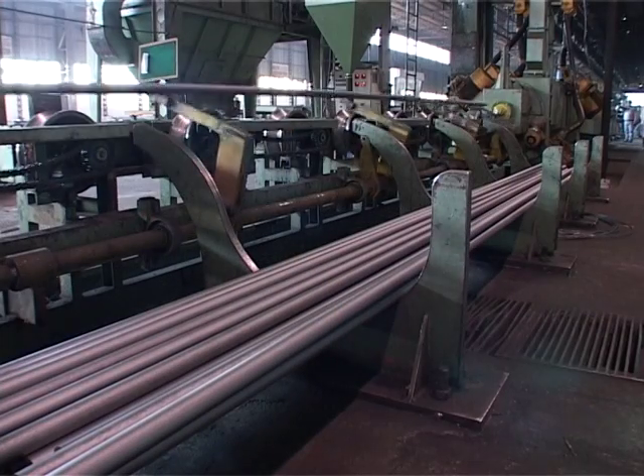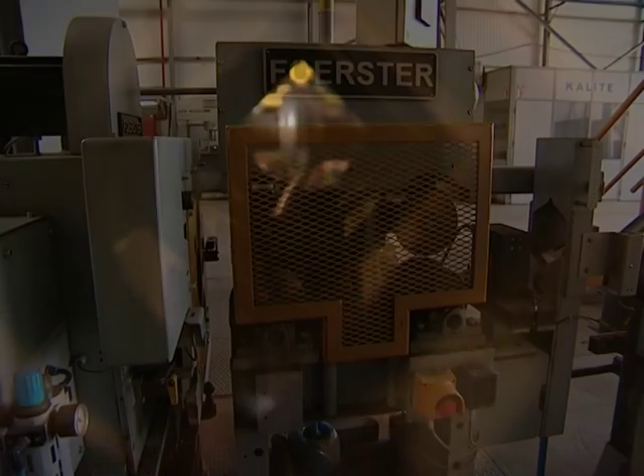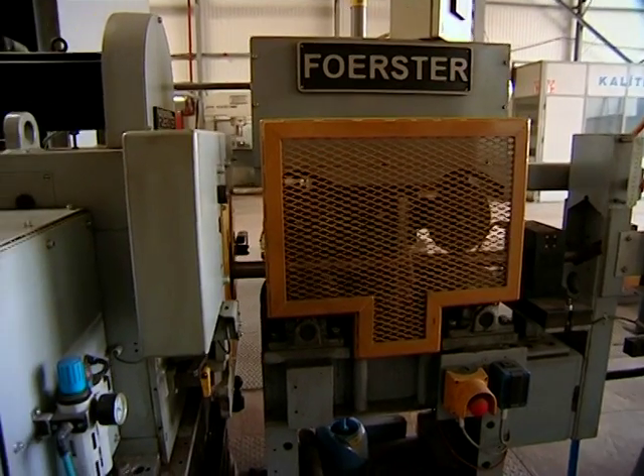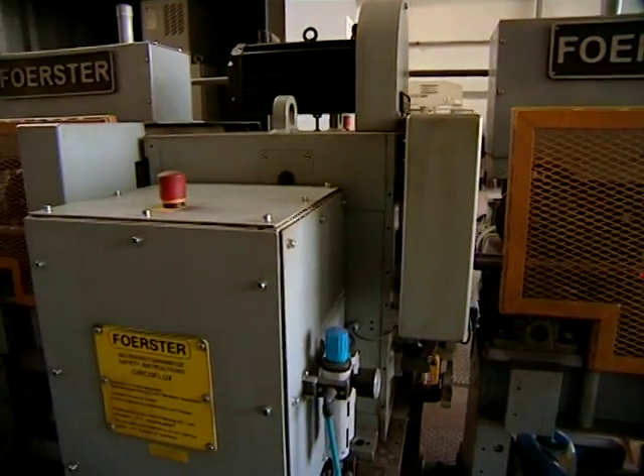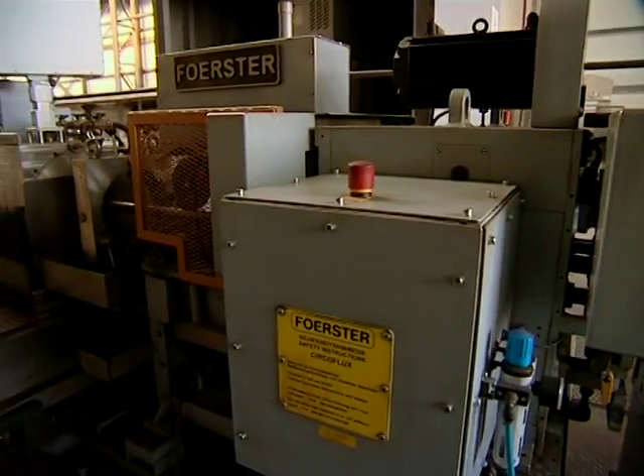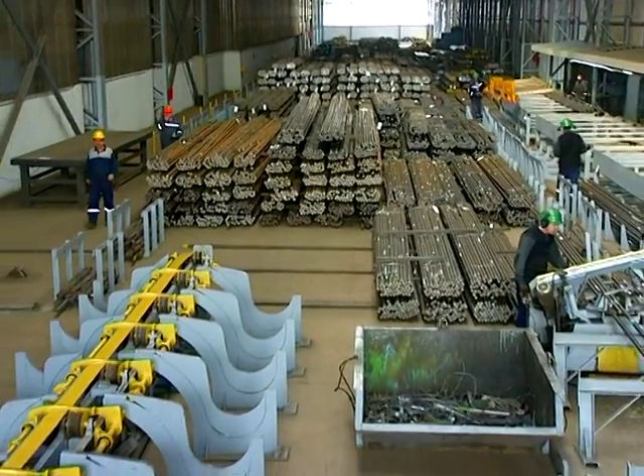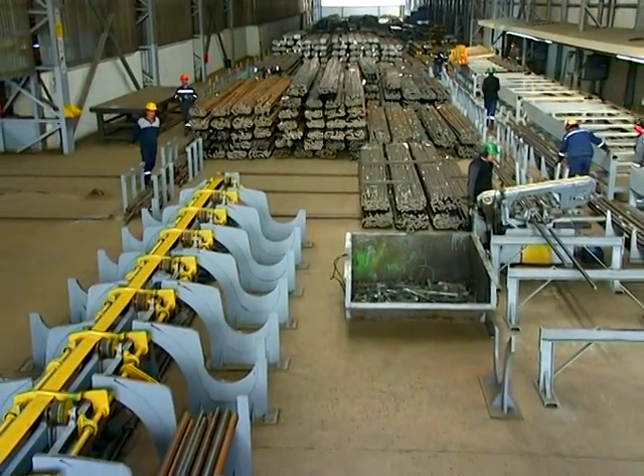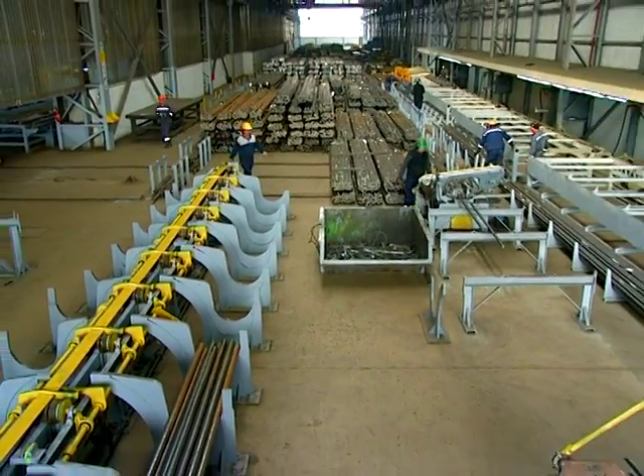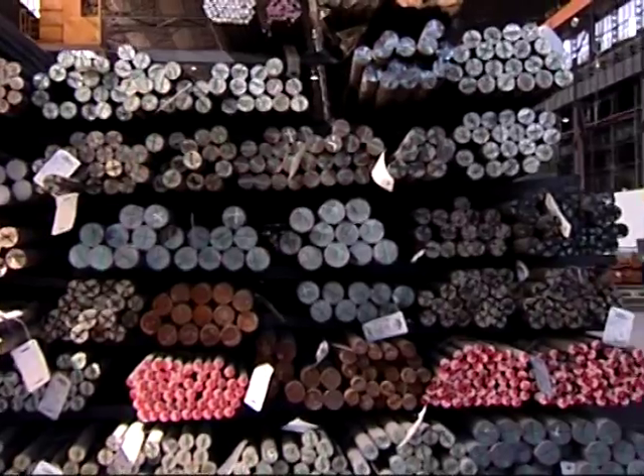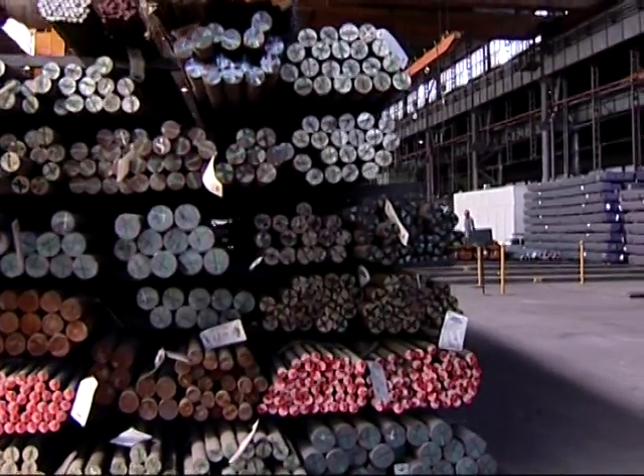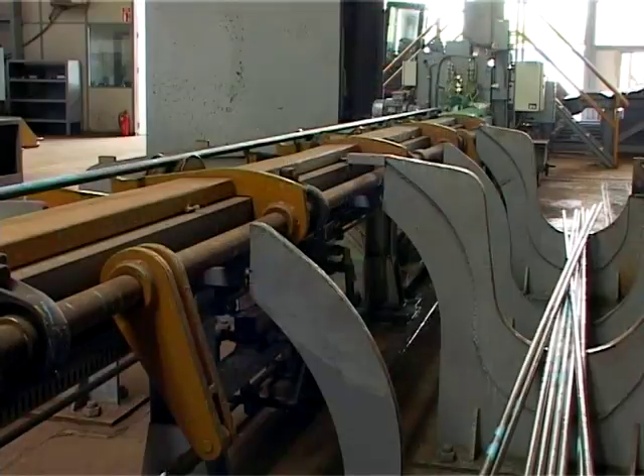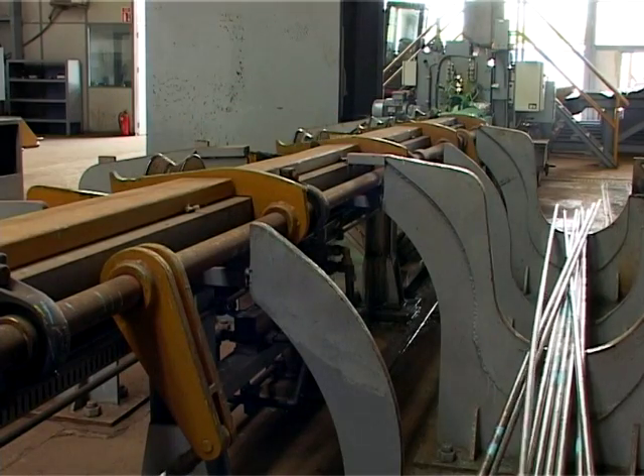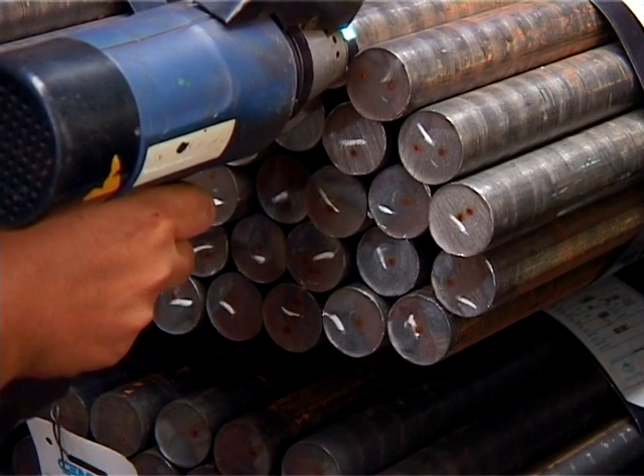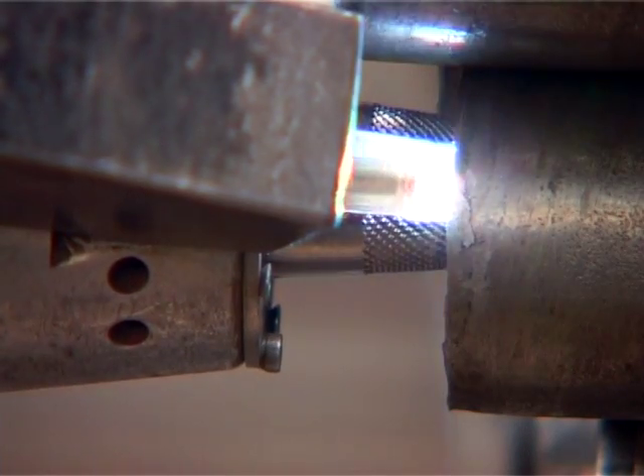Round bars, which are shot blasted and straightened after rolling, are 100% tested in General Electric ultrasonic inner and Foerster Circoflux surface defect detection units, in accordance with EN 10308 and EN 10221 standards. After the detected faults are repaired, round bars are tested again for inner and surface defects. Finally, all bars are tested by mobile spectrometer for anti-mix control, and then transferred to the peeling line.